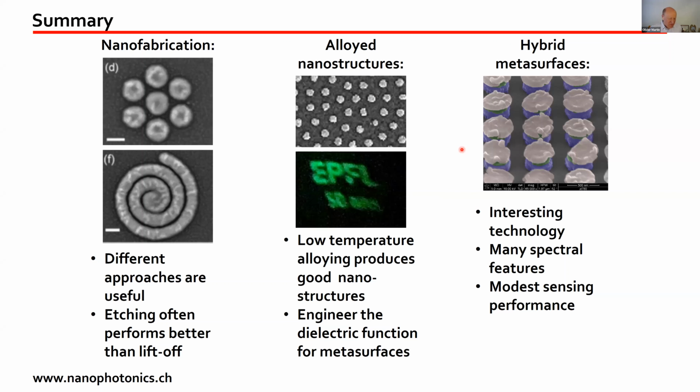You are probably aware of that because you do biosensing, there is a huge literature about gold-silver alloys that are fabricated by chemical synthesis. I think the main applications lie in the fact that by adding a little bit of gold to silver, you can also stabilize the silver chemically. And that has been used, for example, for Raman.